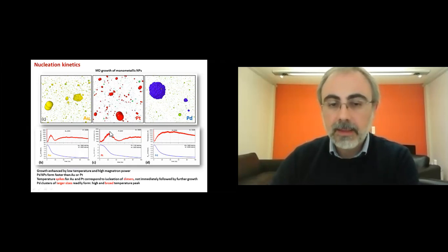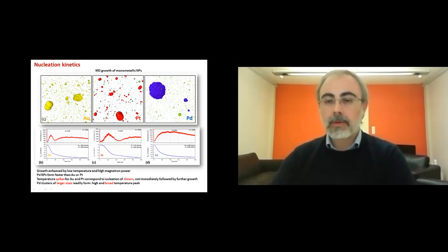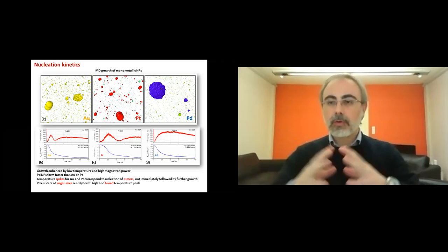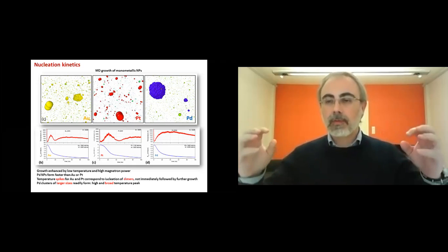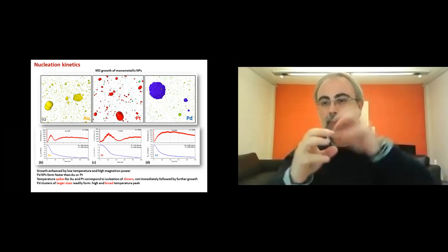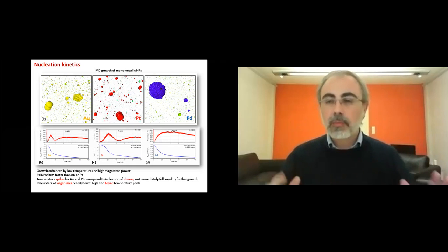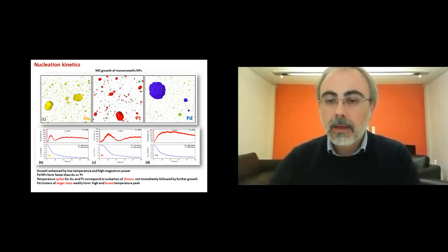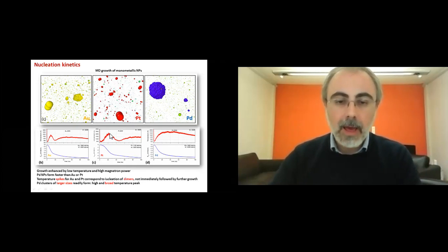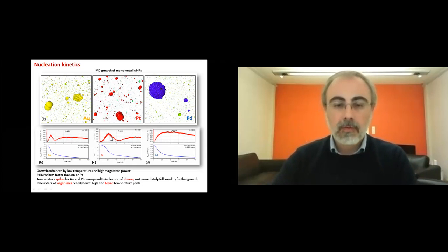The same spike exists for platinum. It's actually even more pronounced for platinum. But this initial spike does not exist with palladium. The reason is that theoretically this spike exists, but since palladium clusters grow so fast, the spike for the creation of dimers merges with one for the creation of trimers, one for the tetramers, and so on. So in principle, you end up having a big, wide peak here, whereas for dimer formation, you only have this very narrow spike for the creation of the dimers.